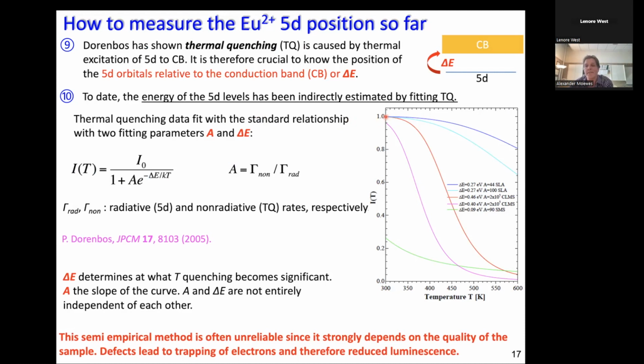So what happens is you see the temperature displayed, and on the vertical axis, only an emulation here, you see the luminescence output and intensity. Now the point is, when you increase the temperature, the luminescence starts to go down. Dorenbos has defined this process. This is believed to be due to the promotion of 5D electrons to the nearby conduction band. It is clear that when you have 5D to 4F as the emission process, it's not advantageous to reduce the amount of your light-producing 5D electrons by promoting them through thermal excitation to the conduction band. So this is called quenching.